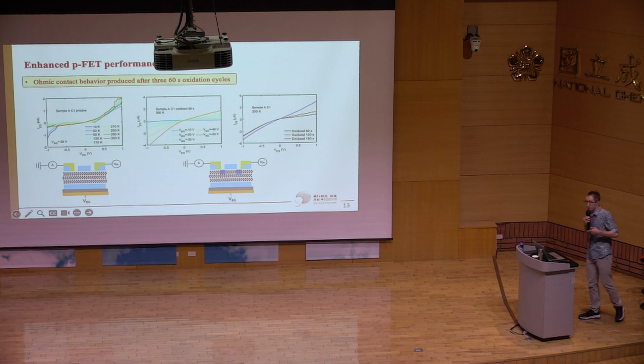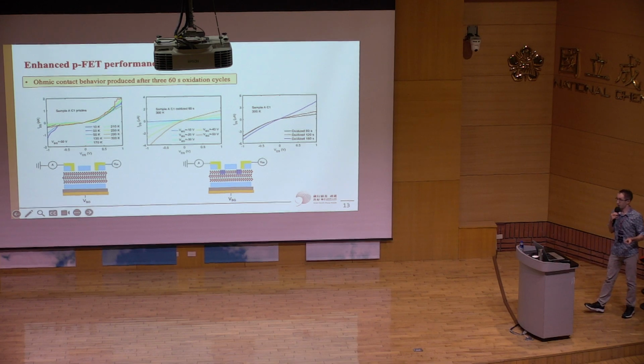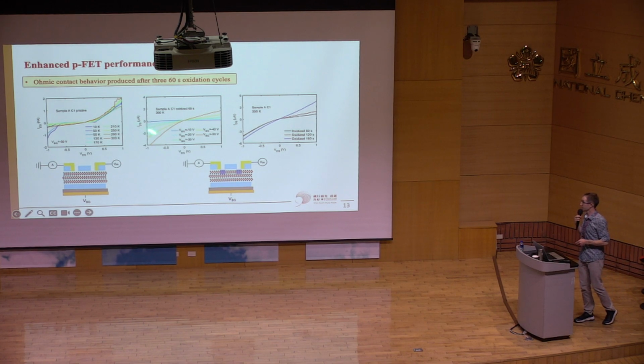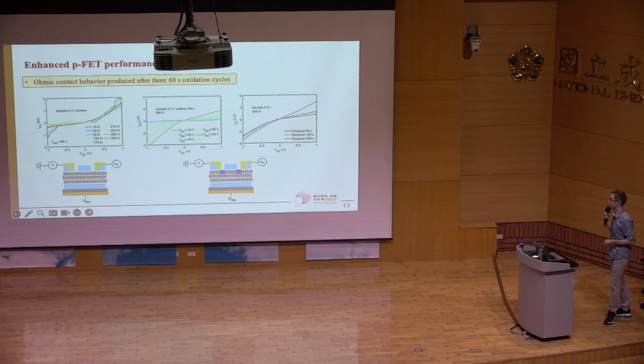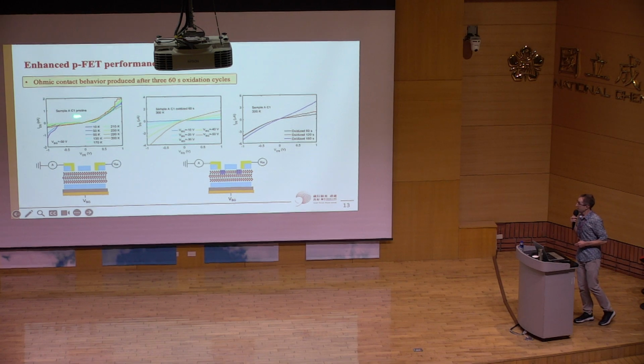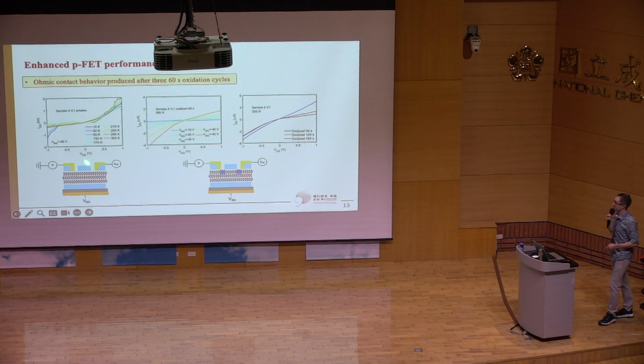Okay. So the previous slides, I've really just talked about one measurement technique, which is to change the carrier concentration, change the gate voltage. Here we're going to use another tool that's available to us, and that's to change the source drain bias and just do these IV sweeps. Before oxidation, if you measure the device at low temperatures, you basically see a flat region around 0 DC bias. So this is indicative of tunnel behavior.